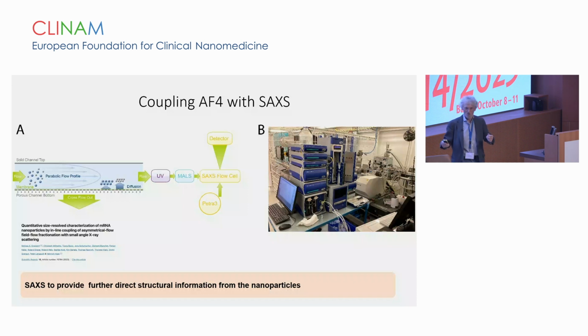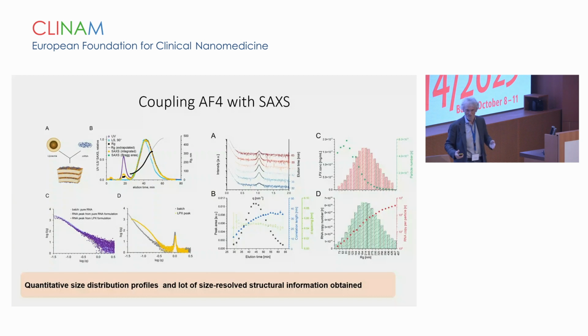And what we did is to combine field flow fractionation with small angle X-ray scattering, which is an intrinsically quantitative method. So per se, X-rays can give you the absolute amount of X-ray scattering material in the sample. And by that, you can quantitatively analyze the samples. You get the absolute fraction in microgram per milliliter of each individual particle size fraction, and you get information on internal structure, morphology, shape, and so on.